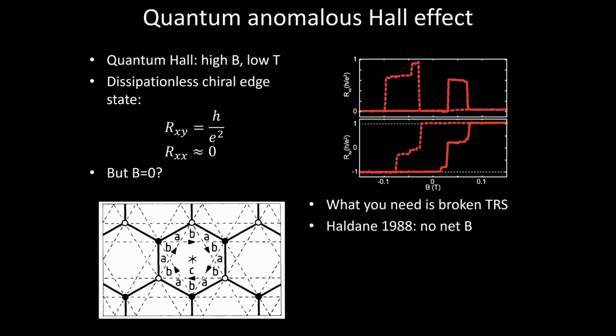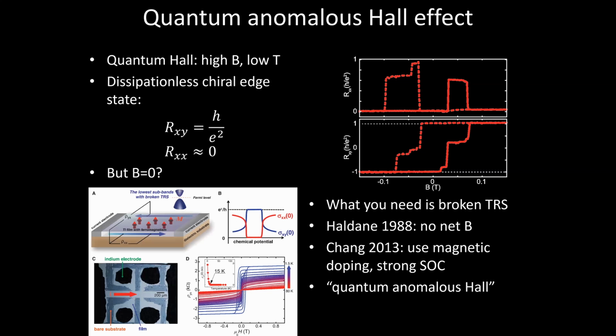And since then, ideas were developed for trying to use just magnetic ordering in a material to break time reversal symmetry and get a quantized Hall effect. Now, in 2013, this effect was seen by introducing magnetism by basically sprinkling magnetic dopants inside a semiconductor that was appropriately designed. It worked. It was a very low temperature effect, and moreover, it became a very disordered system because you had to add these dopants, and it just messes up the rest of the crystal.